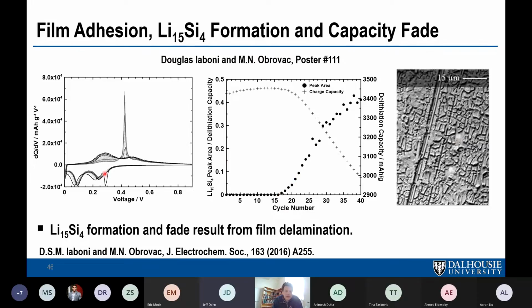So you can see during cycling, this is shifted to low voltage. As we cycle more, it starts to delaminate from the foil and the voltage shifts back up. And then you start to see this growth of the 15-4 phase, and coincidentally you get fade. We believe this is also the mechanism for fade in active-inactive alloys.